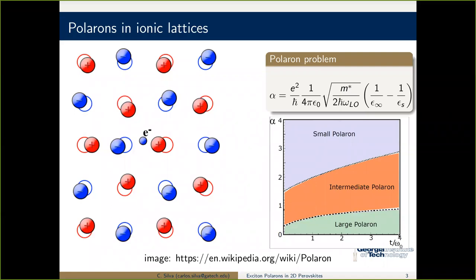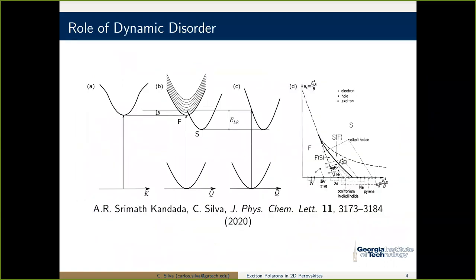This is something that I'm not going to discuss extensively. It's a so-called adiabaticity parameter: to what extent does the coupling to the normal modes of the lattice make the eigenstates of the system. That's a parameter that allows you to say, within these two parameters, what's a small polaron and a large polaron regime. It turns out that in the range that these alphas work out in the perovskites, the hybrid organic and inorganic perovskites, one is in an intermediate regime where short range as well as long range couplings are important. And so let me describe that in a further slide.